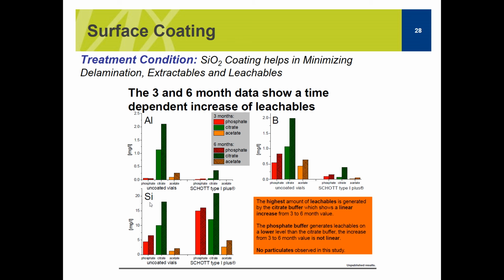Okay, but if we look at silicon, this is a very interesting part. So silicon, the amount that leached in the type 1 plus vials was more than the uncoated vials. So that SiO2 coating itself is leaching. Basically this graph is showing that all of these buffers, phosphate, citrate, or acetate, had interacted with the SiO2 coating, compromised that coating, and allowed the silicon to dissociate and come out into solution. Okay, and this is why it's higher in phosphate, citrate, and acetate buffer.